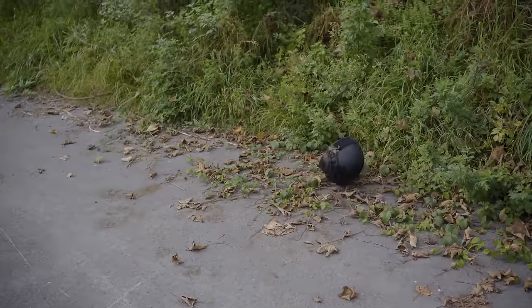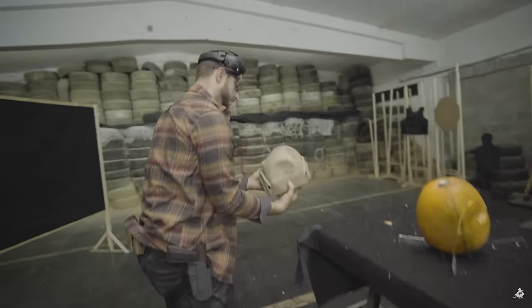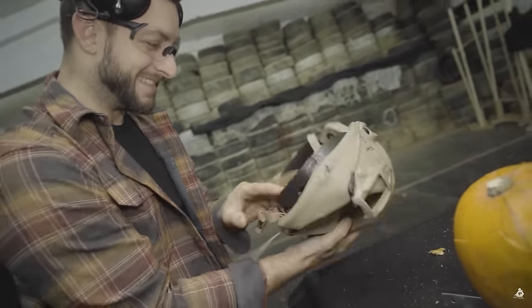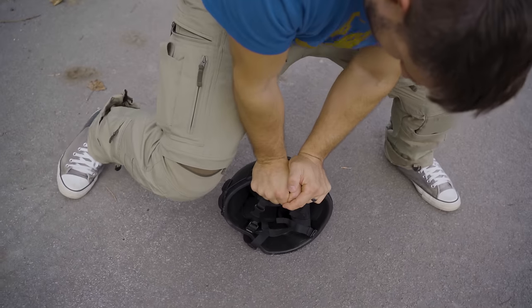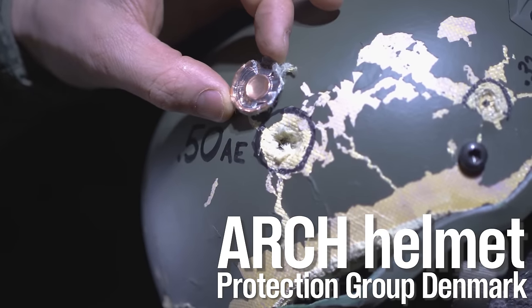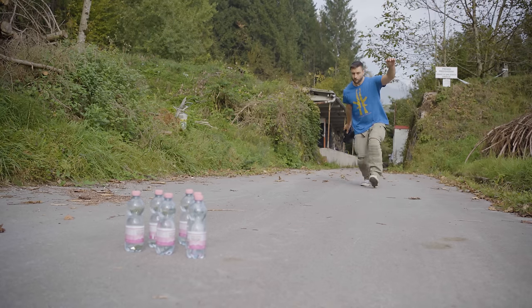This is a ballistic helmet made in China. We already tested one ballistic helmet from China and it did terribly — it was made from high density polyethylene and the biggest problem was that it was not bonded correctly, so when the bullet hit the material it delaminated and the back face deformation was probably lethal. This Chinese helmet is made from aramid fibers, a similar material to Kevlar. We already tested a high quality European helmet made from aramid fibers and it did amazing, so now I want to see if the Chinese-made one can compare.